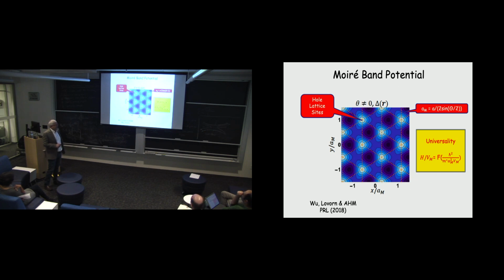And what's more, just as part of the properties of these two-dimensional materials, the layers are not tightly bound to each other chemically. They're just coupled by van der Waals interaction. They tend to be rather far from each other. And so an electron sitting on one layer of material looking at the other layer doesn't see some sharp change as it moves through space. It's seeing the other layer from far away, and so it sees the other layer as something smooth.